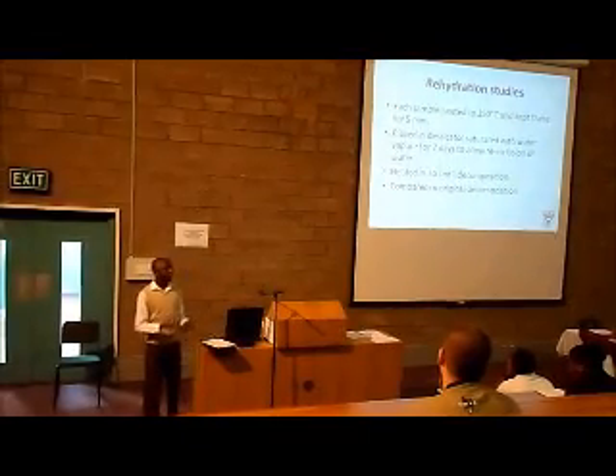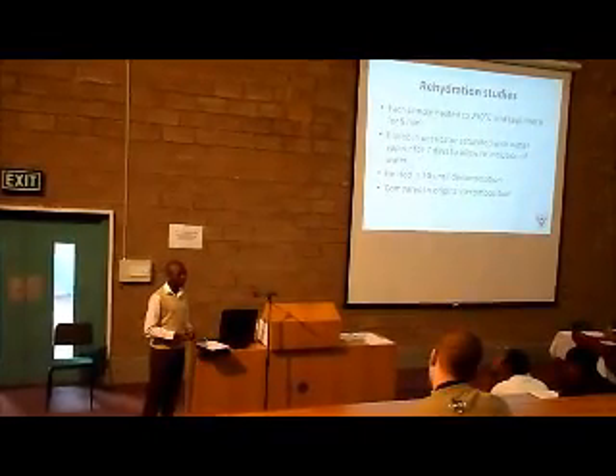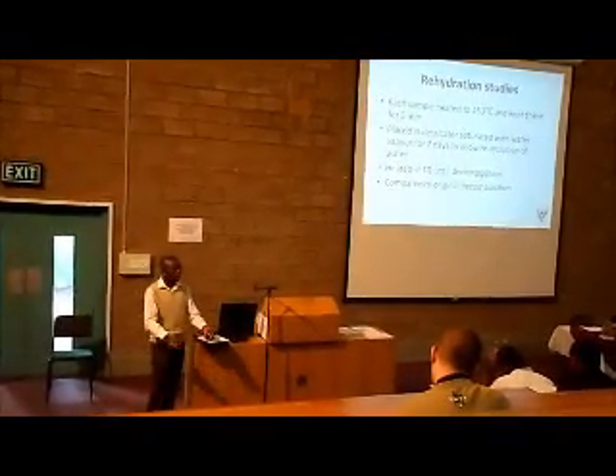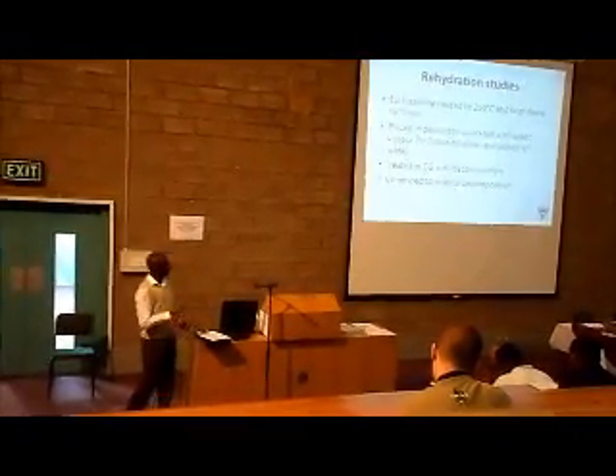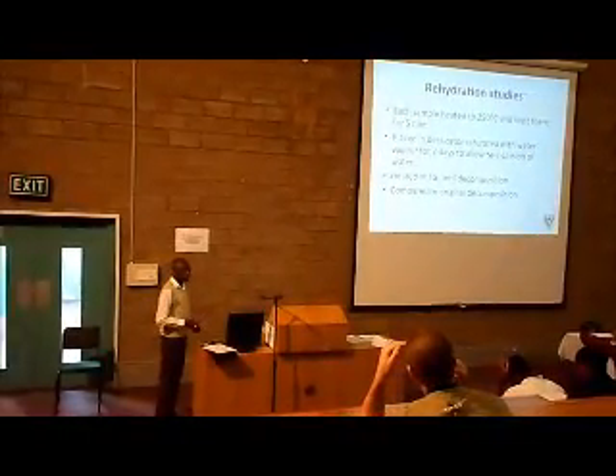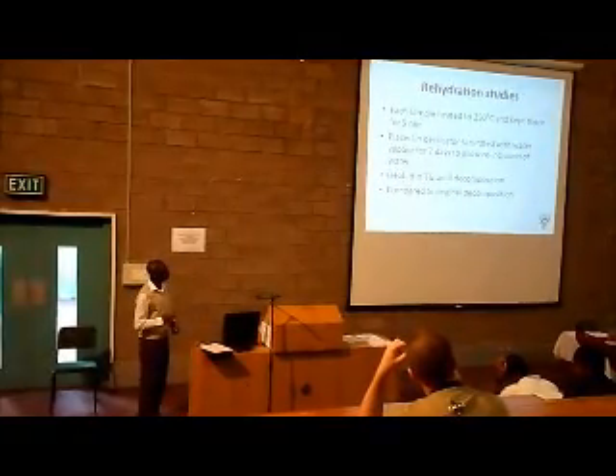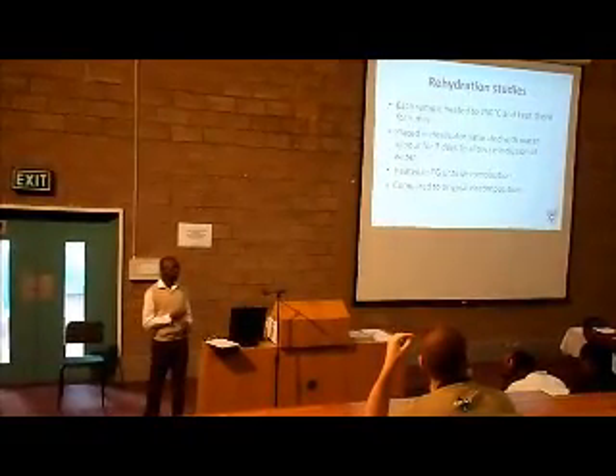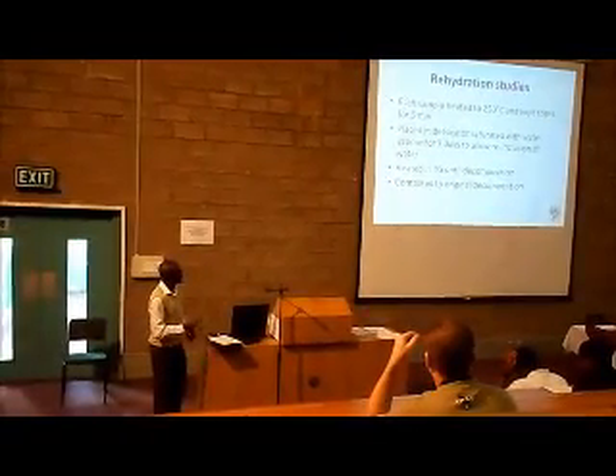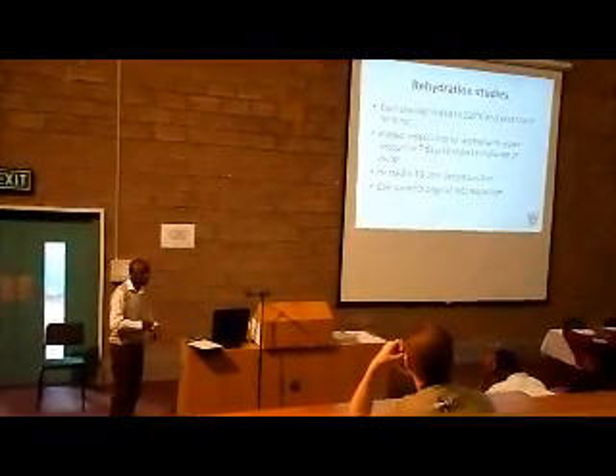Rehydration studies. Now, rehydration studies are important in MOFs because these MOFs need to be reusable. We need to be able to uptake water and then get rid of it and then take it up again. Now, in order to determine the rehydration properties of the MOF, each sample from those products that I've shown were heated to 250 degrees in the thermogravimetric analysis oven, and they were kept there for 5 minutes just to ensure adequate removal of water.